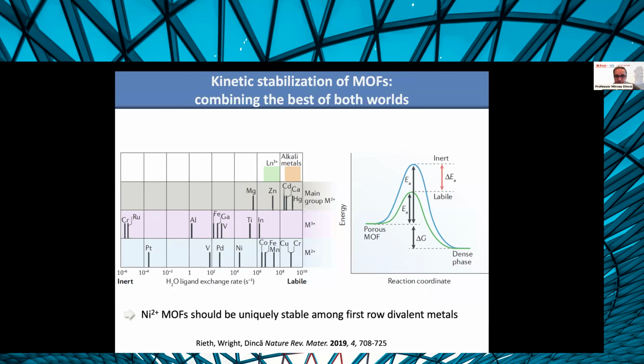Okay, and so basically then, if we understand that, how do we make something more kinetically stable? It could be as simple as looking at a graph that I often show in my freshman chemistry class that says, okay, what is the self-exchange rate of water from a ligand to a solution, or vice versa? And what you'll find is that even within the divalent metals, which are often the majority of metals used in MOFs, you'll have copper 2, manganese 2, iron 2, zinc 2, nickel 2. You can see the difference in kinetics between nickel and copper is almost 6 orders of magnitude.